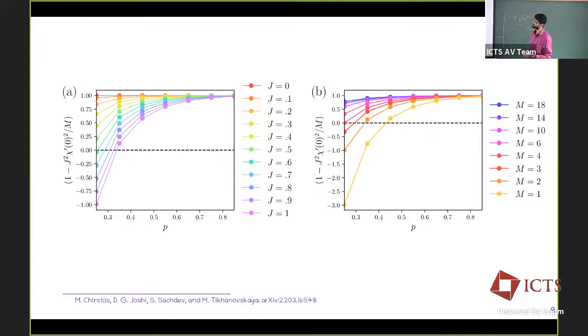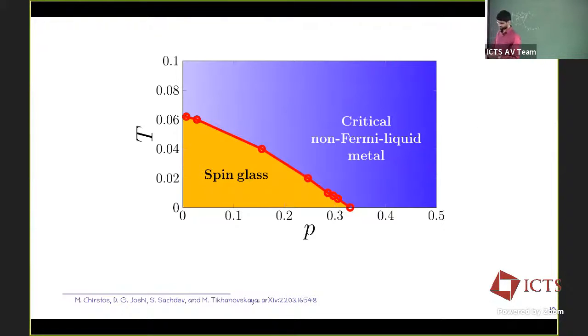Similarly, you can also ask the question, what happens as a function of m? So clearly, if you are strictly in the m equals infinity limit, very large m, there is simply no phase transition. You are always in the non-Fermi-Liquid phase. So as you see from this plot as well, as you increase the values of m, the critical value of doping goes lower and lower, and essentially for m equals infinity, it would just not be possible. So this is just for fun, that for different values of m, you can have different critical values of doping. And then you can also do this at finite temperature, and then you have to carefully do the entire numerics at finite temperature,